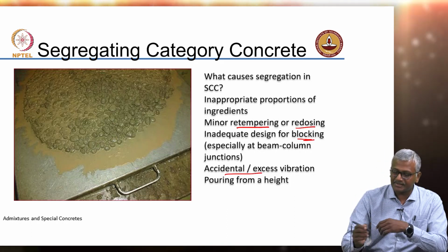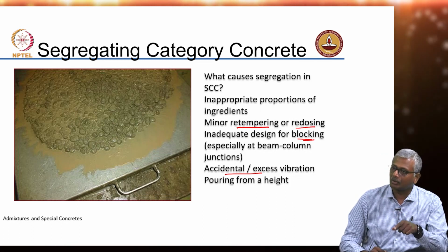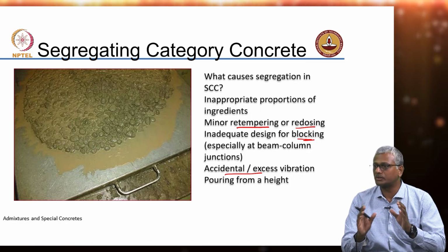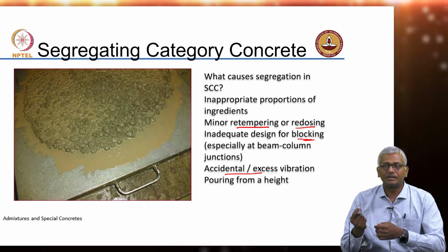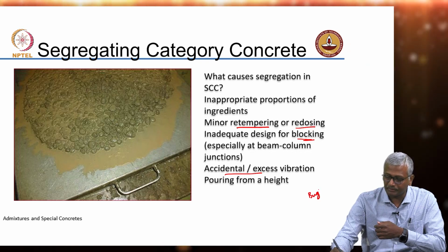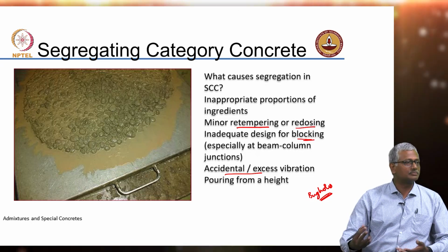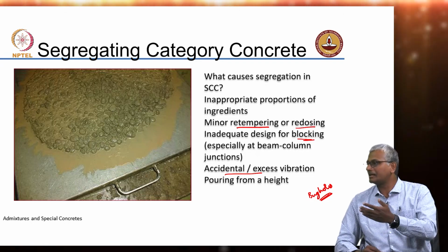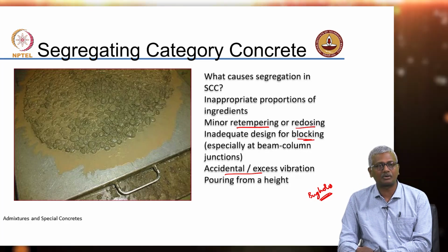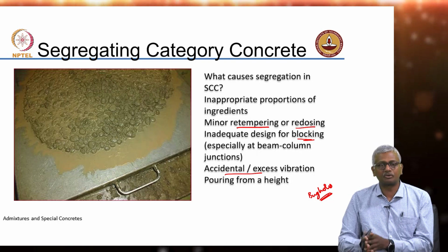And accidental or excess vibration. In some instances, even when self-compacting concrete is used, people tend to use a little bit of formwork vibration to ensure that the surface finish is free of any minor defects such as bug holes, right? Very often you see bug holes on the surface. Those are not really defects in terms of problems to strength or durability, but aesthetically, bug holes are not desired on the surface finish of the concrete. In such instances, it may be beneficial to actually vibrate the formwork.